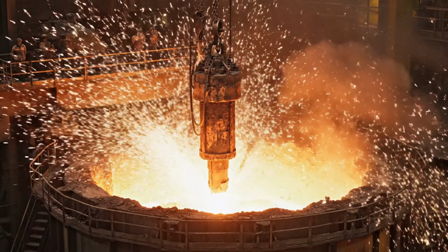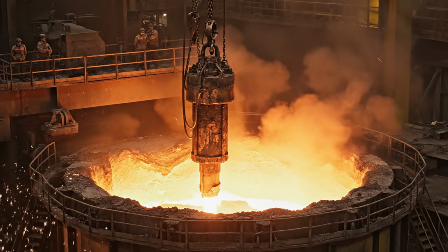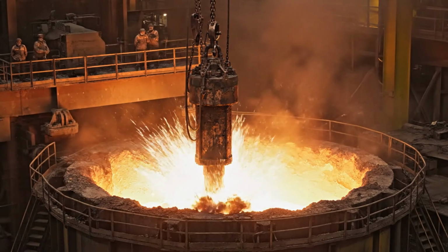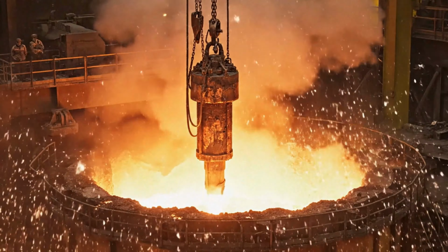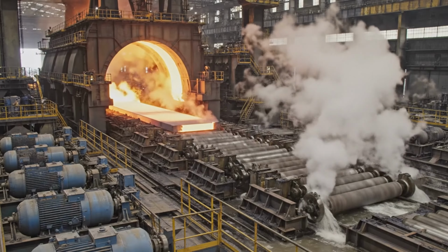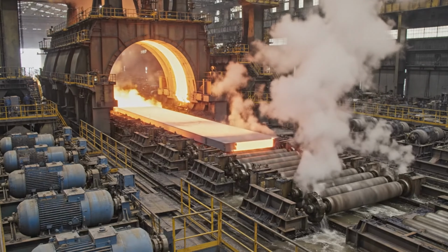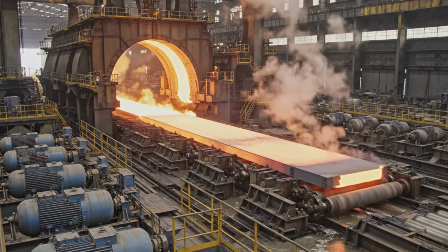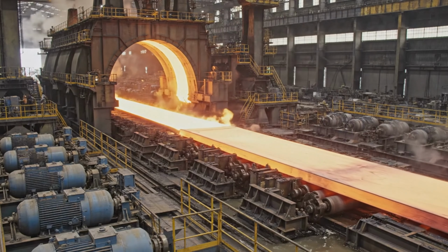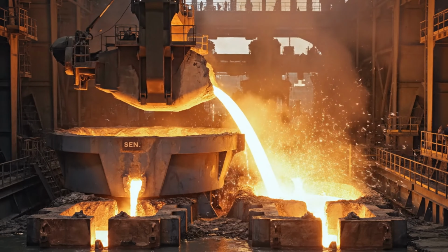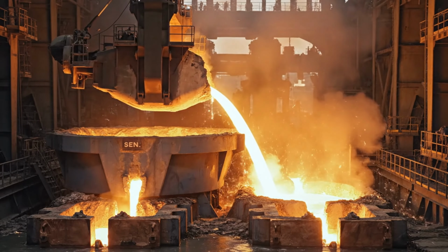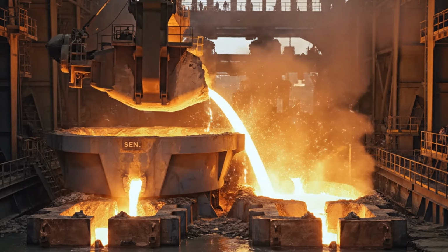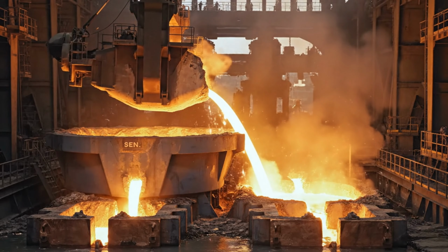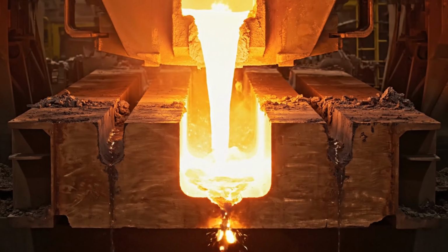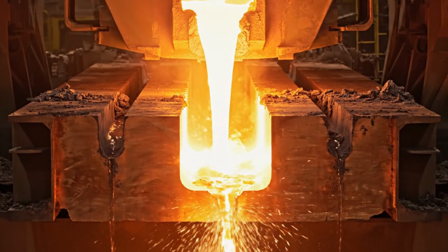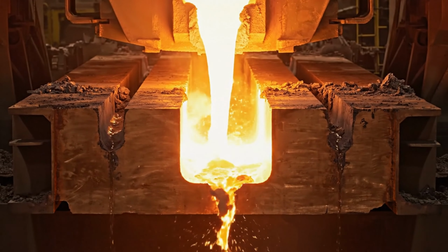The oxygen lance moves into place above the molten bath. The strand follows a curved path, then straightens as solid steel. A tundish sits between ladle and mold to control and stabilize the casting flow. Inside the mold, the outer shell freezes first, while the center stays molten.